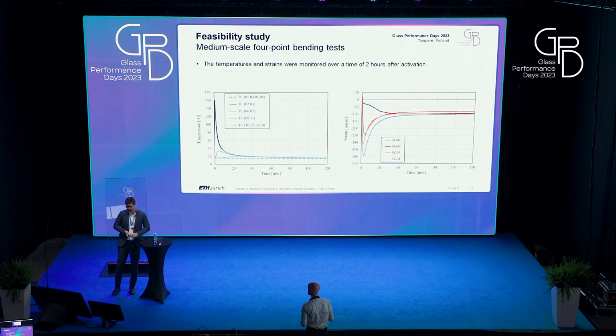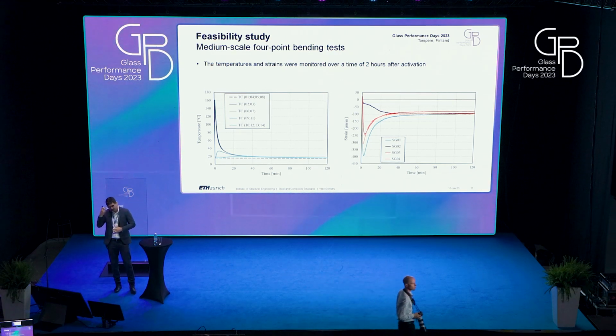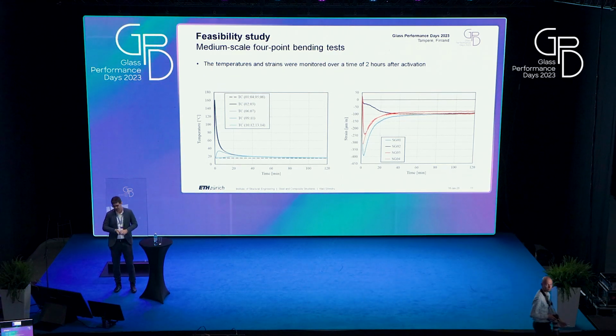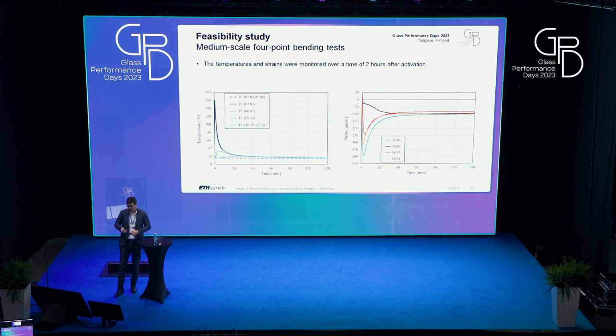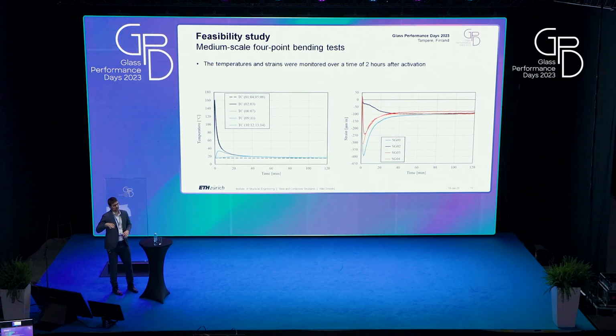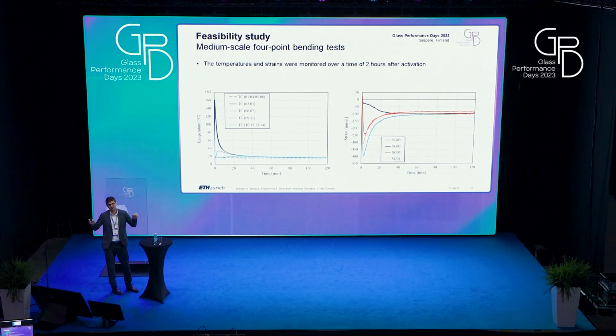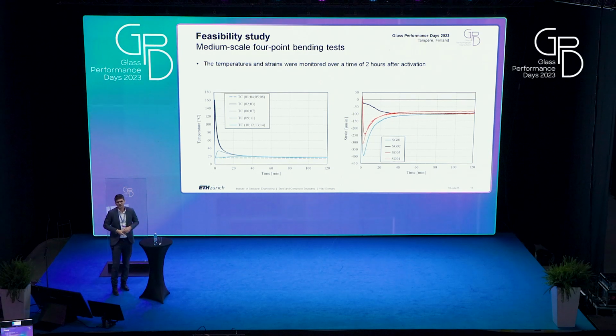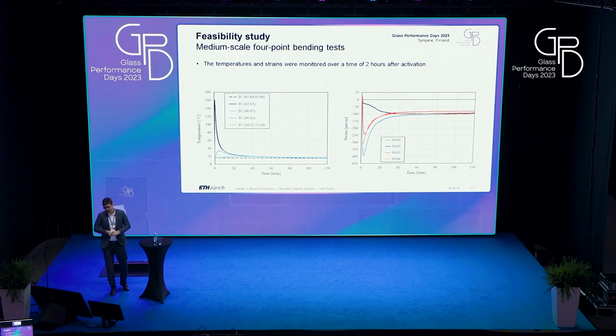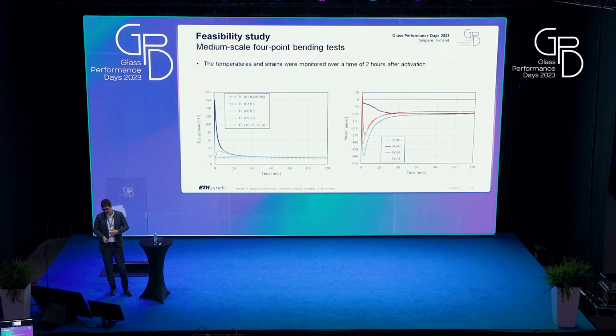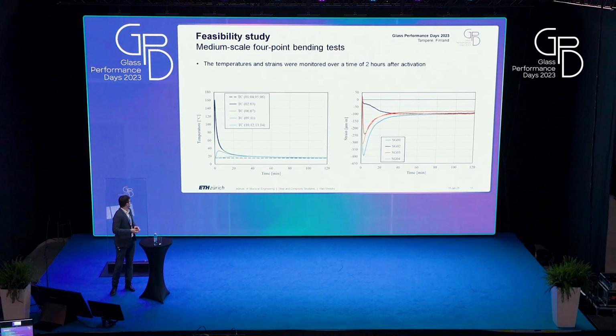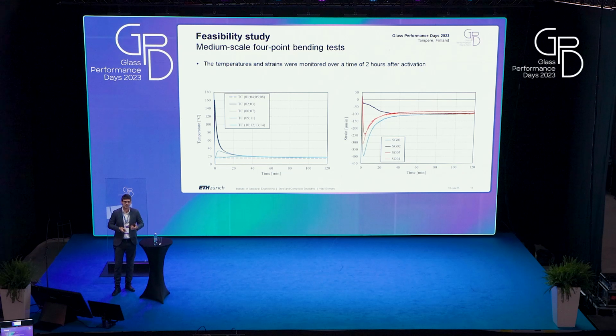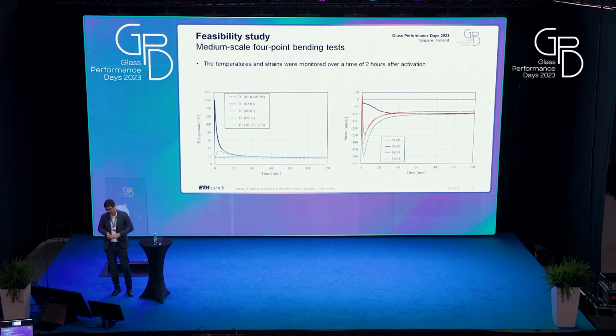If we look at the temperatures and strains that we monitored, on the diagram on the left-hand side you see the temperatures. The black dashed line, which is constant with no temperature increase, was on the shape memory alloys in the anchorage area. This confirmed that the adhesive there will work perfectly. If we look at the glass, we had some heating there, shown by the blue curves, but it was quite low, so we didn't have any problems with thermal stresses.